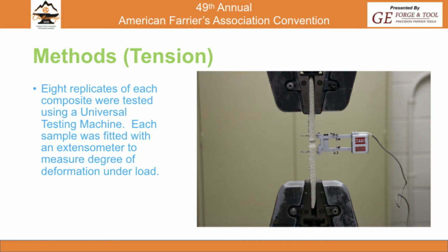Okay, and so they're dog boned in the middle, so when you put them in these Instrons or universal testing machines, they're designed to fail in that spot. So you know where to put your extensometer to measure the stress and strain, or the deformation, in that area. So essentially what this thing does is very controlled and will just pull them apart. So the very slow thing. To break one of these apart, I forget exactly how quick we set the crosshead moving. I think it was 0.5 millimeter a minute. So it takes quite a while for it to break, but very controlled. And then the extensometer measures the stress and strain in that area.